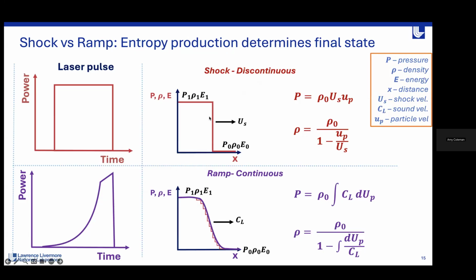In a shock compression, we have this very fast, sharp shock wave, represented by US here, which jumps our state from uncompressed to compressed. So this is a very discontinuous transition, right? And so we're moving from one pressure and density and energy very sharply to a compressed state. By contrast, in our ramp compression, it's not a discontinuous process. You could think of it as a series of very, very small shock steps that are adding together to give this more continuous compression. And so rather than a shock wave tearing through our sample at a very fast shock velocity, we have a compression wave moving at something more like a sound velocity. So this is a lower entropy process. And you can see that this is reflected in the way that we treat our conservation equations. For this process, we've got a couple of integrals in the mix there.